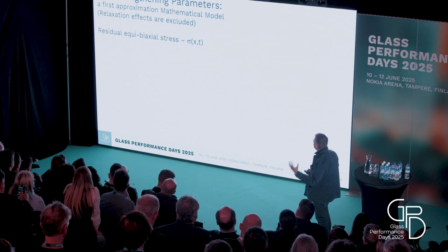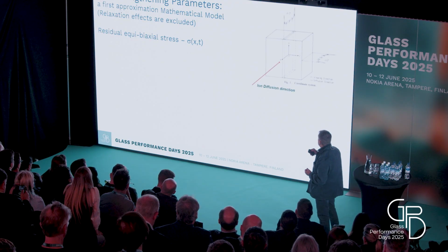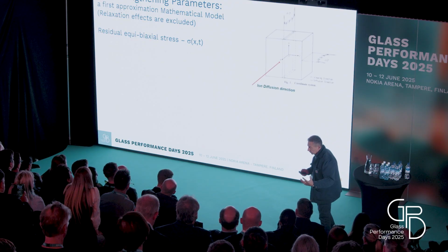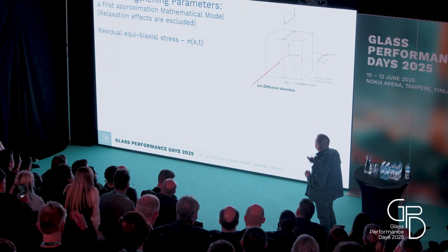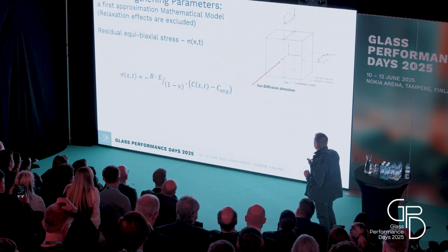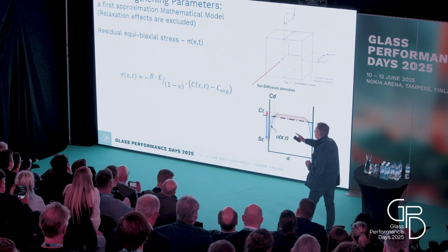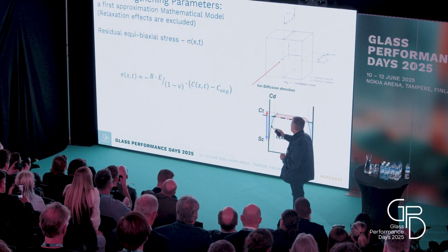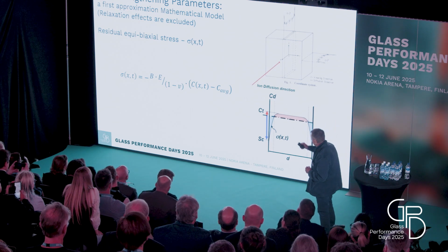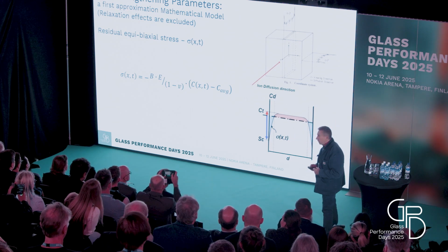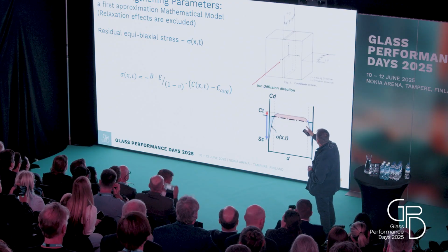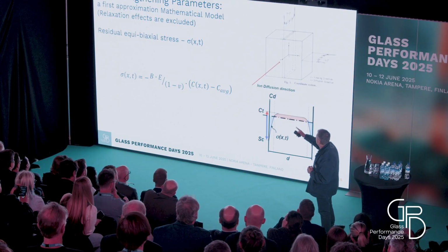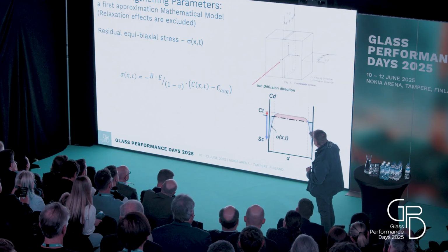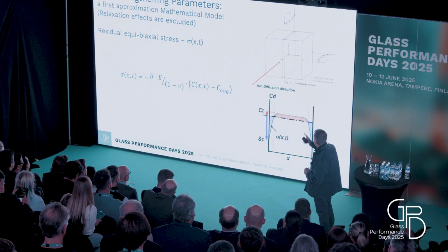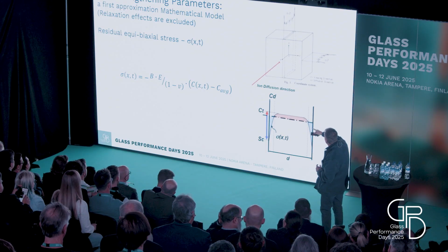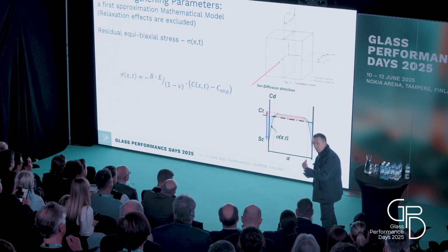So the strengthening parameters. To the point we are interested in mechanics, the equibiaxial stress you see here can be expressed by that equation, and it's just the elastic modulus and the Poisson ratio. It is an analogy with thermal stresses. Stress is a tensor, and the characteristic of this process is that it gives you an equibiaxial stress in that direction. The arrow you see there is the direction of interdiffusion.